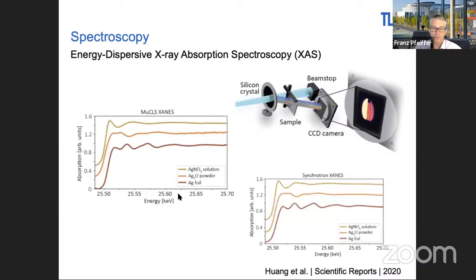And here are some demonstration experiments that show that the MuCLS, the Munich Compact Light Source, can do X-ray absorption near edge spectroscopy measurements that we, for example, did on different oxidation states and different solutions, powder and foil. They give you these very distinct and different wiggles for these different spectra, and they actually look very comparable to what you get at synchrotron sources. And that really opens up a whole new community to address.